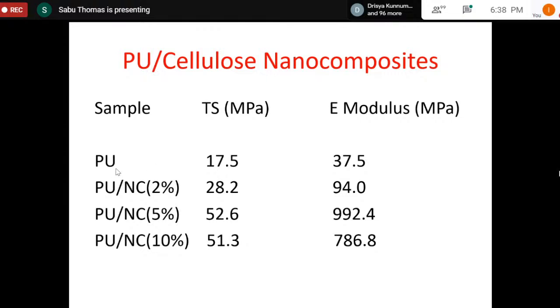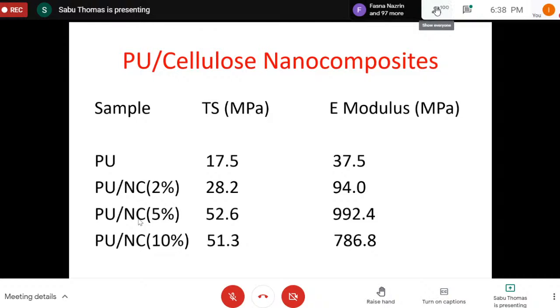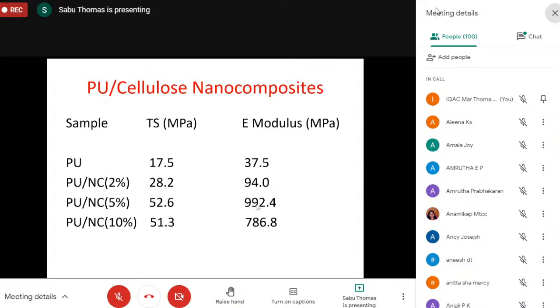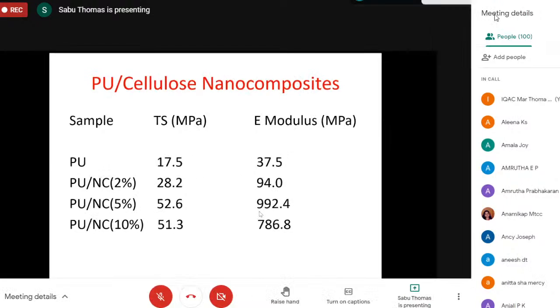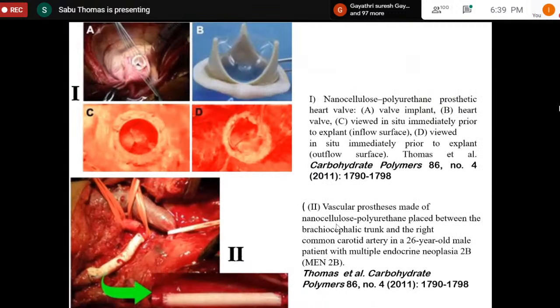You see, the strength of PU is 17.5, modulus is 37.5. We formulated a good work. We put 5% of nanocellulose from pineapple leaf fiber. Look at the 37.5 became 992.4 megapascal. Very fascinating. Eventually, my Brazilian collaborator and I did a lot of work in a Brazilian hospital, and we eventually made a nanocellulose polyurethane prosthetic heart valve. Very interesting material. Eventually we published and we had patents.